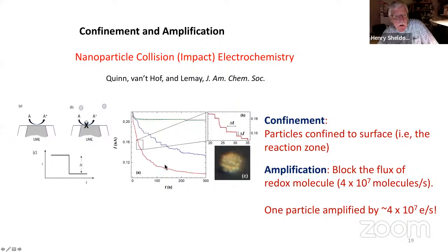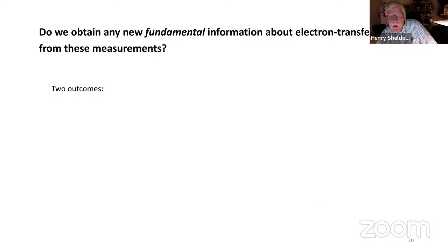All right, let's see. And then going back to the Quinn and Lemay experiment, the particle adsorbs on the surface. So the confinement is you're putting a particle right at the sweet spot where the flux of the reactant molecule is highest. All right. And the amplification is you're blocking the flux of the redox molecule. So these steps here, if you take the current, these steps correspond to blocking the flux of the redox molecule, corresponding to a flux of roughly 40 million molecules per second. All right, so the amplification here is on the order of 40 million. Each particle blocks the flux of 40 million molecules. All right, this is true in all of single molecule, single particle, single reaction redox electrochemistry.